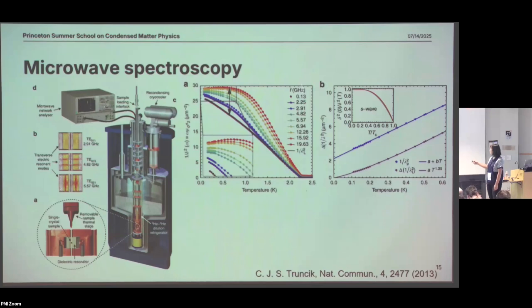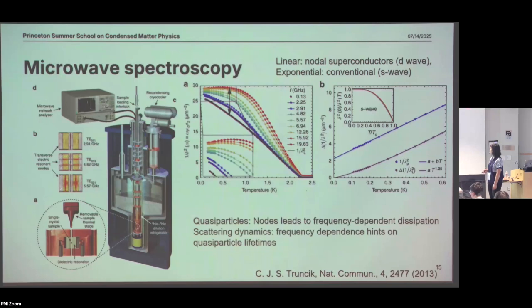You can also see here that they measured at different frequencies from 0.13 to 19 gigahertz or so. All those different frequency measurements can also tell you something about the quasi-particles and the scattering dynamics. Here, the linearity has to do with the nodal superconductor. But the nodes can also lead to frequency-dependent dissipation, even from very small frequencies, unlike in the case of S-wave superconductors. So through measuring sigma 1, they got information about these quasi-particles, and the frequency dependence always has the quasi-particle lifetime in it, just like in the Drude model for a common metal. Here it's similar, so you can get a handle on what the lifetime is.